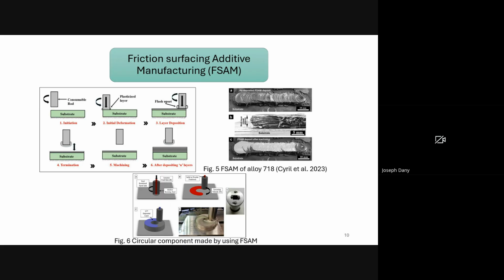Several factors control how good your coating is. The rotation speed of the mechtrode controls how much heat is generated, which plays a big role in how well the coating bonds. Moving the substrate slower causes a thicker layer, but means the material stays hot longer. Increasing pressure, pushing the rod down, improves the bonding, but also makes the coating thinner and wider. The size of the mechtrode mostly controls the coating width, but needs stronger machines for bigger rods. And in multi-track coatings, positioning the rod properly is key to avoid defects where tracks overlap.